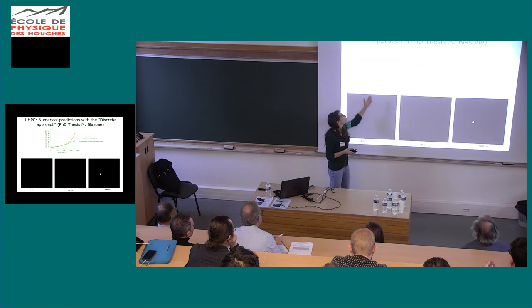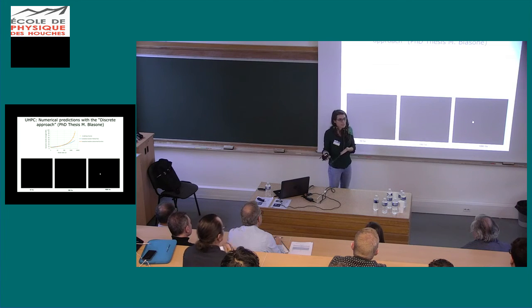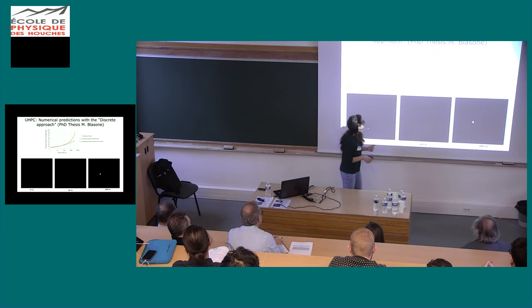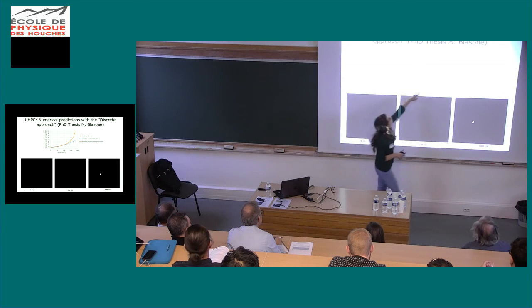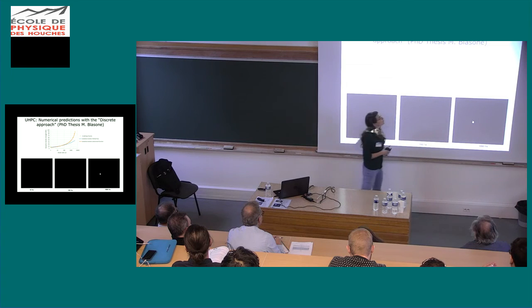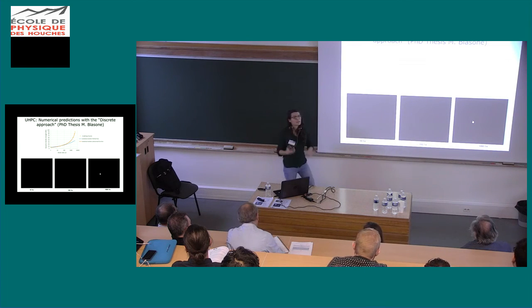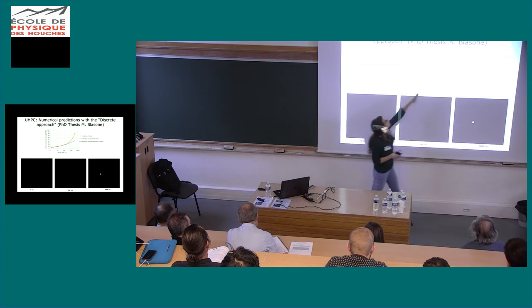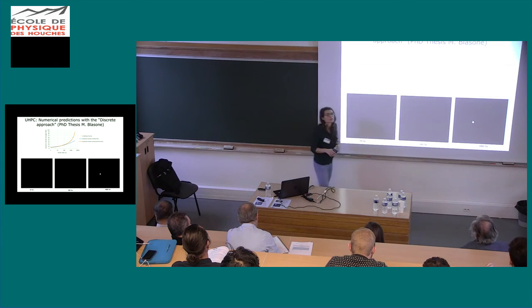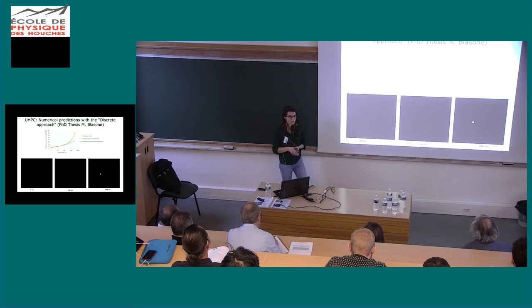And the reason is just one: we calibrate our model with the scale parameter from the bending test that activates just the bigger pore. We could not go further here because we need a scan with higher resolution, because the last point that we observe is when we initiate all the pores.